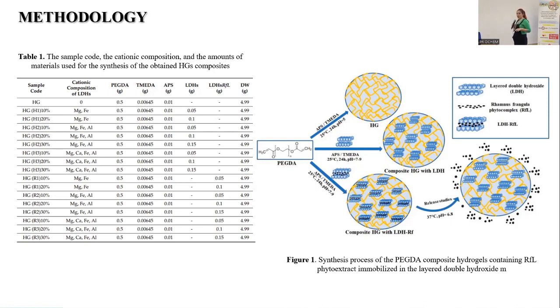At the end of the reaction time, the vials were broken, the hydrogels were recovered, and they were cut into small discs. For the purification step, these discs were put in excess distilled water for 7 days, and the water was changed every day in order to remove the unreacted products. After the purification, the swollen pieces were dried at 40 Celsius degrees until they reached a constant value and became aerogel.